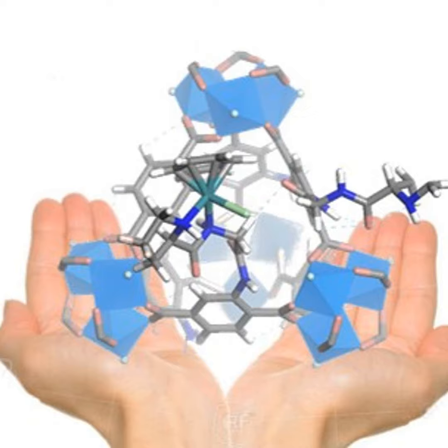So we've got our catalyst attached to our MOF, ready to do its thing. What happened when they actually ran the reaction? Did it work? This is where it gets really interesting. It worked amazingly well, actually. Oh, how so? So get this. The MOF-based catalyst showed like 3 times higher enantioselectivity compared to if you just used the same catalyst without putting it inside a MOF. 3 times? Whoa, that's a big difference. So it wasn't just making the reaction kind of work. It actually made it way more precise.